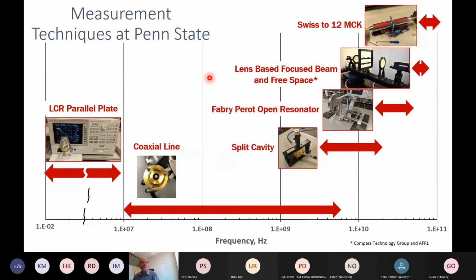More specifically, these show the techniques we have at Penn State and collaborators shown here. So here we're plotting frequency, and we're going from basically 10 millihertz all the way up into the terahertz range. So again, looking at 13 orders of magnitude of frequency, and it's pretty valuable from the materials standpoint to look at this frequency range, because generally dielectric relaxation mechanisms are very broad and they span many decades of frequencies. So to have this capability is helpful when we're trying to understand loss contributions to materials and how to basically lower those loss contributions.